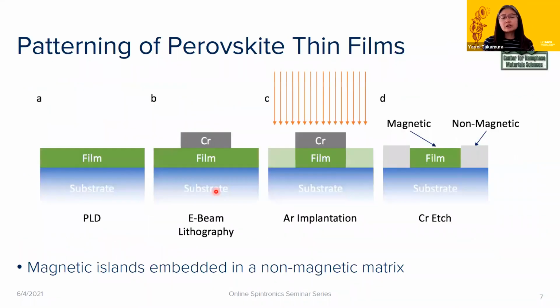And for this talk, not only do we care about thin films, but we wanted to pattern these materials into nanostructures or microstructures. And the way my group has been doing it for the past 15 years is, rather than an etching-based technique, using a flood argon implantation in order to define our structures. So basically we take our thin film and pattern, using electron beam lithography, a chromium hard mask into the design of whatever pattern we want to result in.